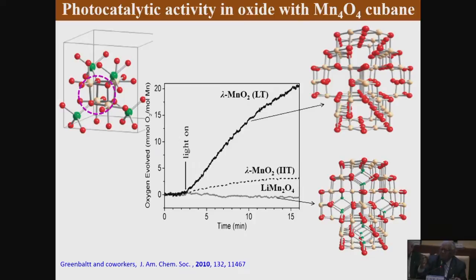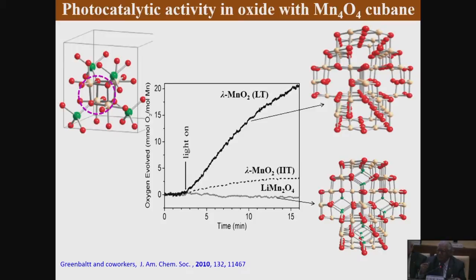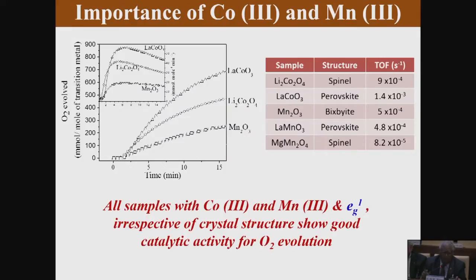Because of this, people in Princeton and some other places made artificial structures — cubane structures of manganese and so on — thinking they could produce oxygen in the laboratory using such catalysts. But actually, when we did this work, we found that what they had said was not correct. When we used their cubic manganese oxides of various kinds, we did not get as much oxygen. So we devised a new way of producing oxygen, finding that systems using cobalt and manganese were better.